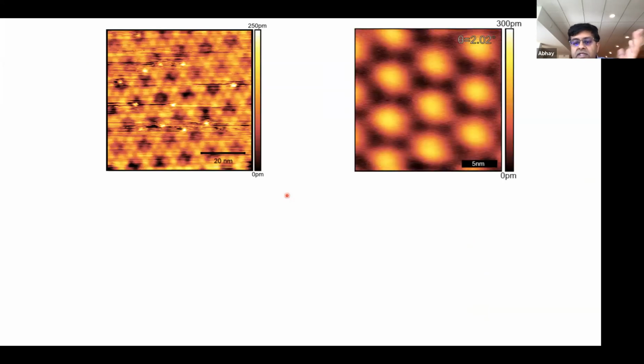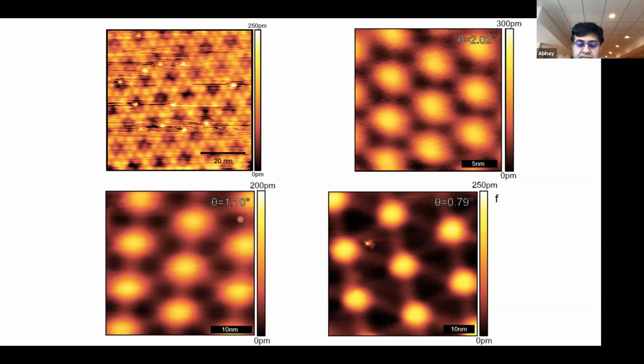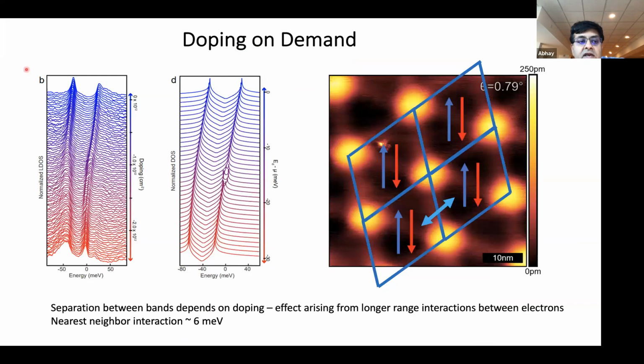Okay. And so we went through and we made a bunch of these samples with different angles until eventually we hit this magic angle of 1.1 degrees that MacDonald had predicted and where superconductivity had already been observed. And we were able to measure the spectrum of that particular sample. I don't want to take you through this since it's sort of old work. Just to say that the spectrum clearly showed 2 Van Hove singularities, exactly like MacDonald had predicted. The energy spacing of these Van Hoves was not exactly what MacDonald had predicted, but it was not a huge surprise in the sense that MacDonald's calculation was a very simple calculation.